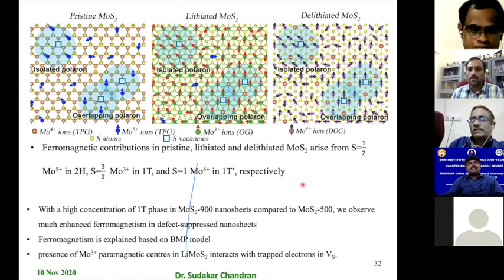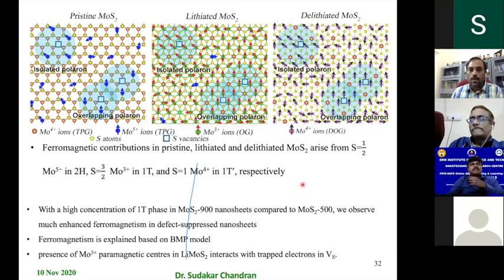What is the typical Curie temperature of these samples? Yeah, so for example, what we found is like 120 Kelvin, but there are people who have also shown a very high temperature for this. Of course, it has not been found experimentally, but they extrapolate the temperature dependent magnetization curves and then try to find the Curie temperature. I forgot the number, but a high temperature has also been proposed for this. But the system people have studied is slightly different, where they have a MoS2 phase, something like this. They don't have this situation where sulfur defects and paramagnetic moly are there because of the defect nature. What they have is, locally, a 1T phase. Means in MoS2 you have a trigonal bipyramid